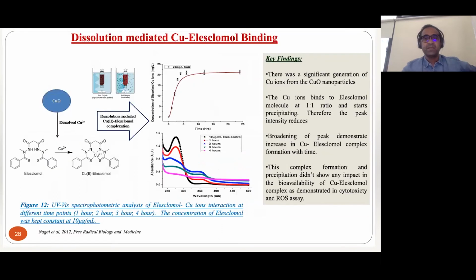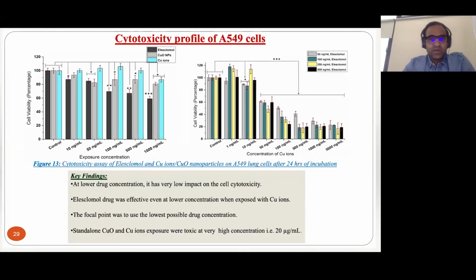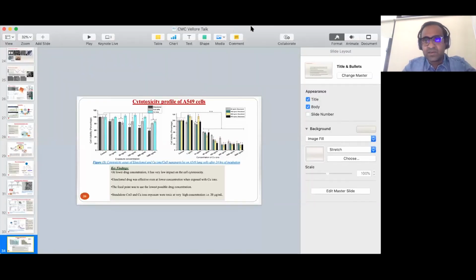Okay. So what we did is that we tried to attach this elesclomol to these copper ions because they have a very high binding affinity with copper ions. And then we tried to find out whether these are getting trafficked inside the cell and really causing cell death. So we took an A549 cell model. A549 is basically a cancerous lung cell line. And what we tried to see is, by changing the amount of copper oxide nanoparticle, copper ions, and elesclomol, whether we are actually getting a different cell viability. And what we see is that if we look at, just let me minimize the screen because these control buttons are hiding the icons.